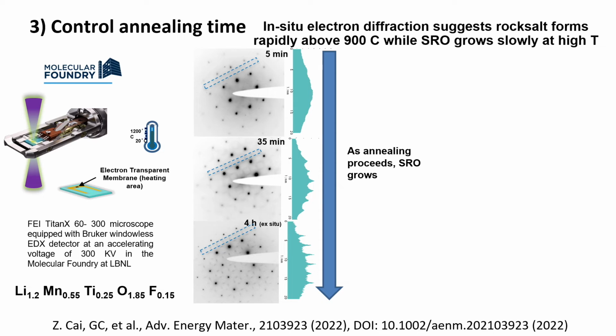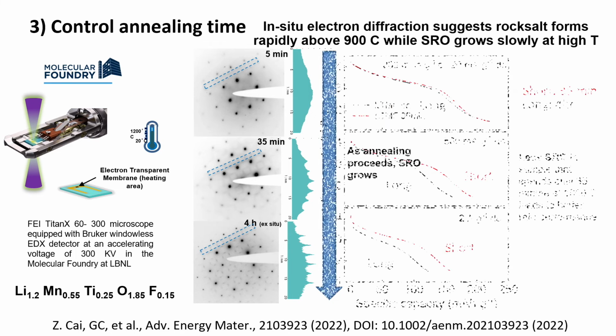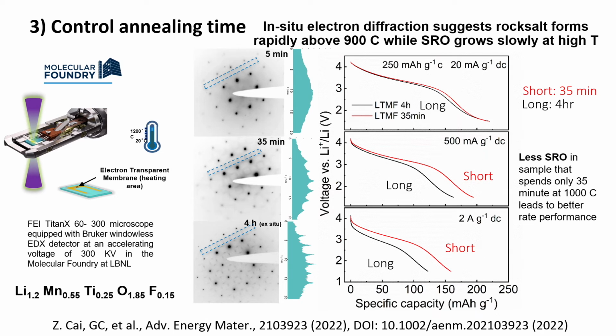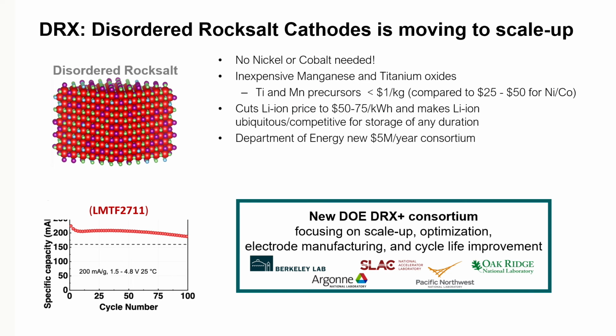See, this is 5 minutes. You already have the Bragg peaks of the rock salt, but when you go to 4 hours, you start getting a lot of this sort of short-range order streaking. And indeed, the materials that have short annealing times, even with the same particle size, always have higher capacity because they have better rate performance. Okay. So this is an example of where we went from basic science.